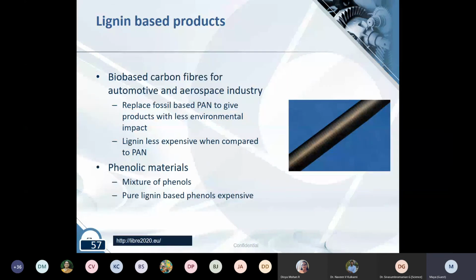Other applications of lignin, and a very interesting application, is the development of bio-based carbon fibers from lignin. Currently, carbon fibers are derived from PAN, polyacrylonitrile, which is petroleum-based, and which is also very expensive. So there are projects right now where people are thinking of using lignin to develop the carbon fibers. So then you have a bio-based feedstock for the development of carbon fibers. As I mentioned earlier, lignin has a number of phenolic groups, so you can derive bio-based phenolic resins from lignin.